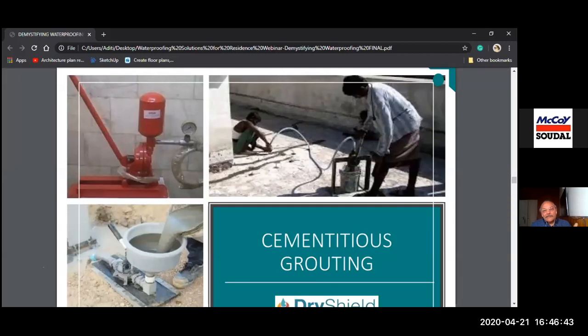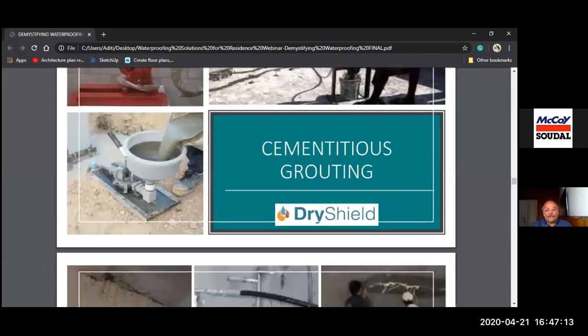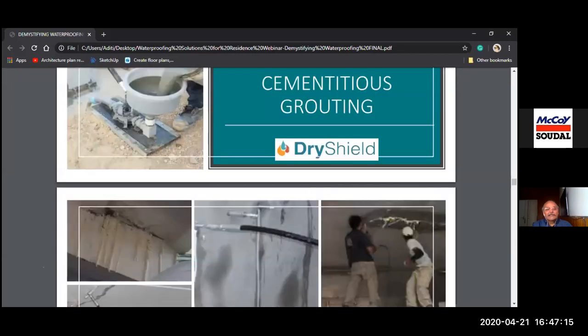It does what it has to do. It is non-shrink, expandable grout, added with admixtures like crystalline admixtures, and it has fibers also. It will fill almost all the joints in the concrete wall. Maybe with the bigger voids there'll be some problem, but otherwise 90% of the wall will be filled with this. So for minor repairs where the water seepage is minor, this is good.